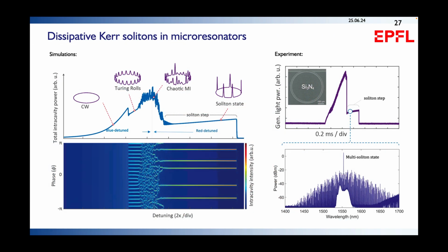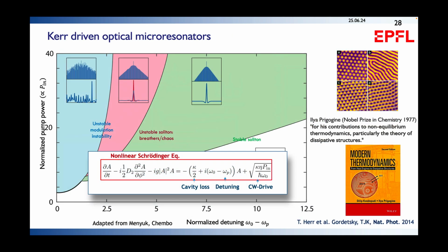And so the way the soliton formation proceeds is you tune the resonator into resonance, you start to generate these so-called Turing rolls, then a chaotic regime, and then in a moment where you tune across resonance, actually all the waveform collapses into either one or multiple solitons. And you can switch actually from 5 solitons to 4, all the way down to the single soliton state.